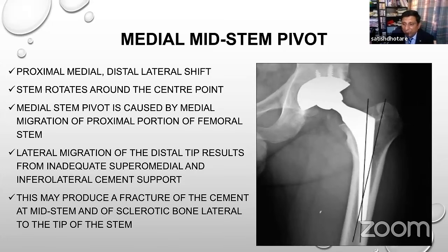Now, medial mid-stem pivot. So basically the pivot is in the medial side of the mid-stem. What happens is, proximally on the medial side and distally on the lateral side, there is a toggle or a movement. So the tip of the stem is laterally hitting the cortex, which is causing some sclerosis. And similarly, there is more load and pressure coming on the medial side, on the calcar side. The stem is pivoting around the center point somewhere here. That causes medial migration of the proximal end and lateral migration of the tip end, which leads to instability and pain, and depending upon the load and pressure, it can either fracture or break, secondary to these changes.